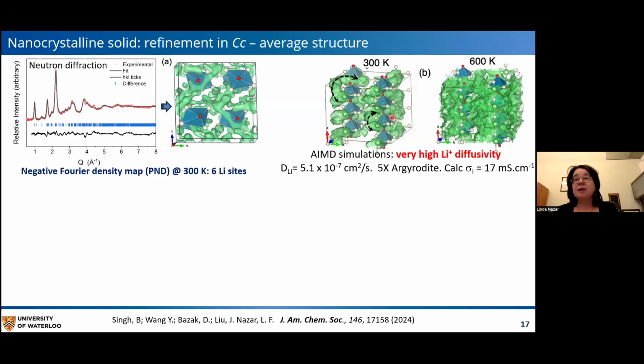This shows the probability isosurface at 300 Kelvin and at 600 Kelvin. And you can see that even at 300 Kelvin, it's just a very good dispersion of the lithium. And a diffusion coefficient we calculated of 5 times 10 to the minus 7 centimeters squared per second. And this is 5 times that of argyrodite. So this is a very, very highly conductive material. And the calculated conductivity of 17 is a little higher than that experimentally, of course, but that's to be expected.